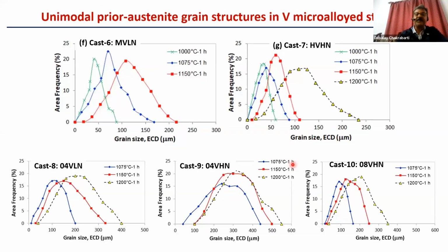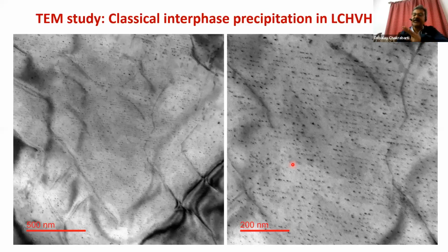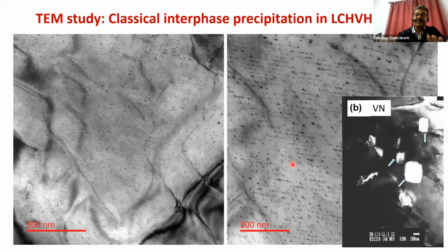And then after rolling, you will find the grain size becomes very fine and uniform, and precipitates remain very uniformly distributed. These are very fine precipitates, the vanadium carbonitride interphase precipitates that we have found in our steels. You can see this is called interphase precipitation, uniform precipitation. In all the grains you will find it's the same because of the lack of segregation of vanadium, which is the advantage. And it gives very good strengthening.